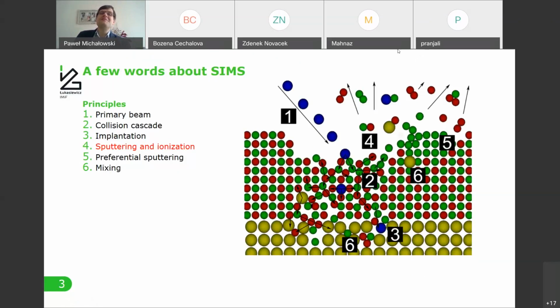Usually when we talk about secondary ions, obviously we need some primary ions. The technique is basically about the bombardment of a flat sample with primary ions, which causes various effects to occur. The first is that these ions transfer their kinetic energy to the atoms of the sample, knock them out of their stationary position, and transfer part of their energy to them, and these atoms start to move on their own. They also collide with other atoms from the sample and transfer their energy to them, and start their movement. In this case, the so-called collision cascade is generated.